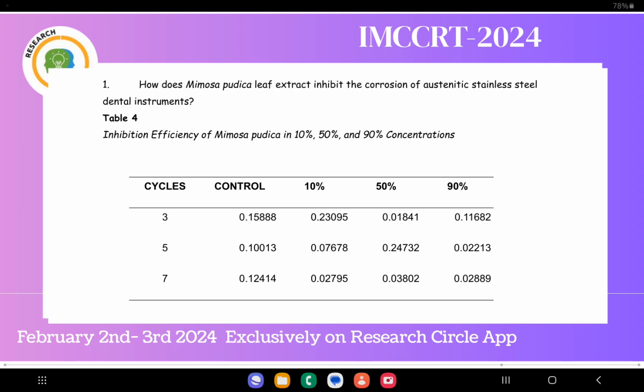Analyzing concentrations, the 50% concentration surpasses others in cycle 5, while the 90% concentration demonstrates greater stability. Variability exists across concentrations and cycles, indicating complex interactions. In cycle comparison, the 50% concentration has the lowest efficiency in cycle 3, but the highest in cycle 5, and efficiencies tend to decrease for 10% and 50% concentrations in cycle 7.